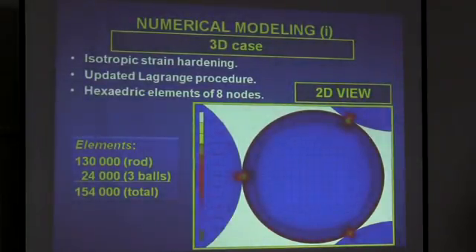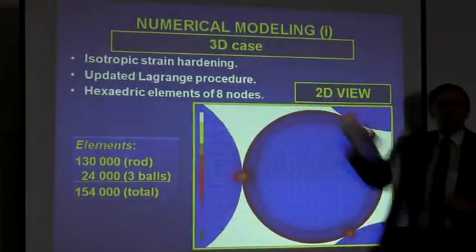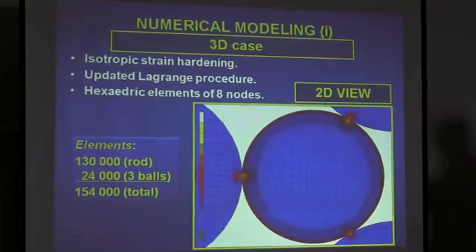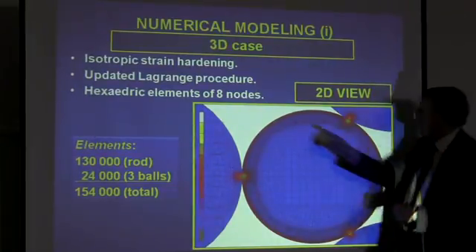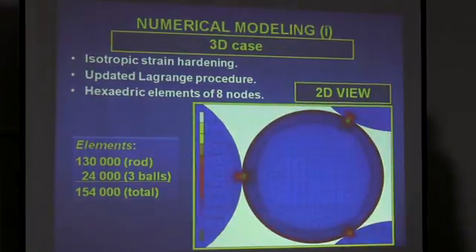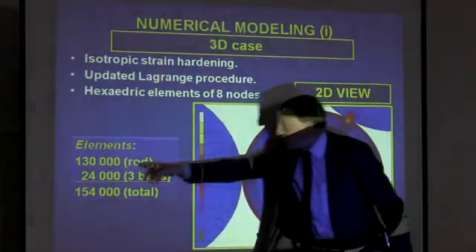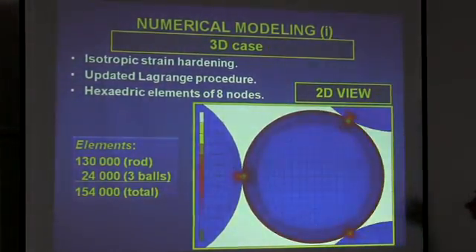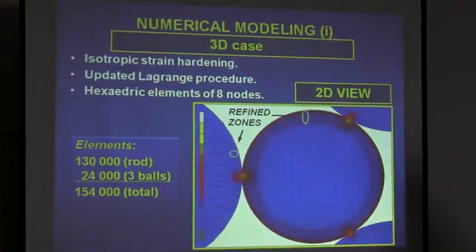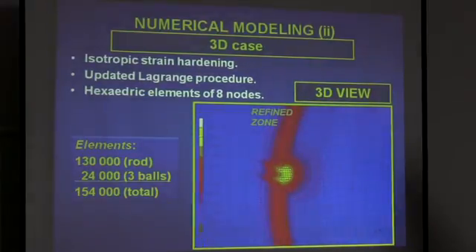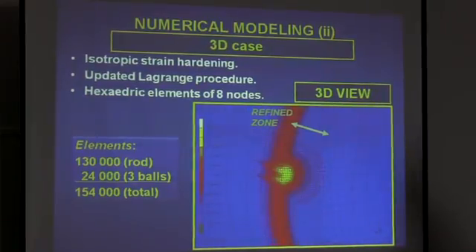For the numerical modeling in the three-dimensional case, we assume isotropic strain hardening. We use an updated Lagrange procedure, we update the geometry, and we use hexahedral elements of 8 nodes. This is a two-dimensional view, with as many as 130,000 elements for the rod and 24,000 for the three balls. More than 150,000 elements. Very detailed mesh, with refined zones, and this is the refined zone in the three-dimensional case. Let's go with the computer. It takes time, I think.